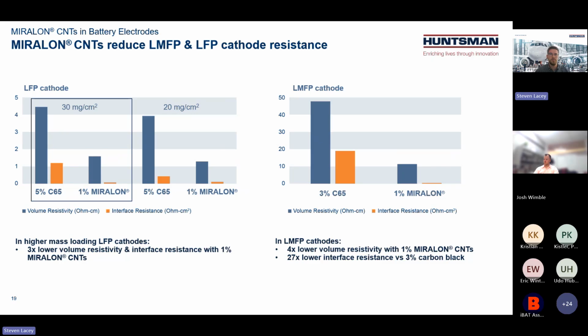Now, when we are trying to enable LMFP cathodes, which also have a very low conductivity naturally, and also at different mass loadings, we can see that for LFP at a higher mass loading, we also have a noticeable improvement in volume resistivity and interface resistance. And in an LMFP cathode, when you compare it to carbon black, we also see a significant decrease in interface resistance as well as volume resistivity at a much lower loading of carbon. So you can essentially have more active material in your cathode, and it could enable higher energy densities.